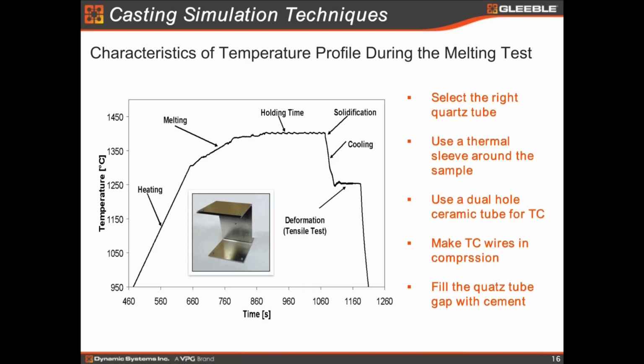Okay. And then the second thing is, as I mentioned before, that no matter what you do, when you have a metal, you have a thermal gradient from the surface to the center, right? Even though you control where the resistivity actually is, so that it's isothermal in a vertical plane. But again, you still need to minimize the radiation and the convection heat loss. Because if you do have a thermal gradient from the surface to the center, you might end up with a hole after solidification, as you have seen from the ingot casting. You have some holes at the center of the ingot because of the thermal gradient. And that's the same for this kind of testing.